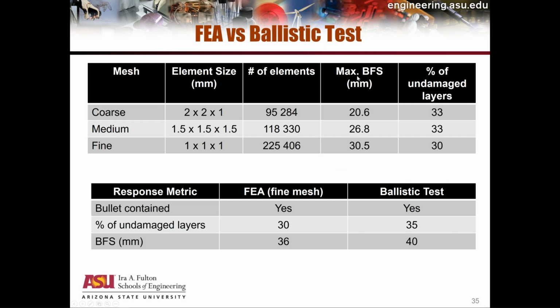In each one of these cases, we use 2 metrics to see how good the prediction is. The first one is called back face signature. The NIJ standard says if the back face signature is greater than 44 millimeters, the plate has failed the test. That means for a typical person wearing body armor, if the bullet is arrested within the armor but the back face signature is 44 millimeters or more, it's going to leave a huge mark on the skin, and it is possible that the internal organs may be damaged. So that is the reason why you want to limit the back face signature to 44 millimeters. Why it is 44 is another webinar, but that's the standard we have to follow.